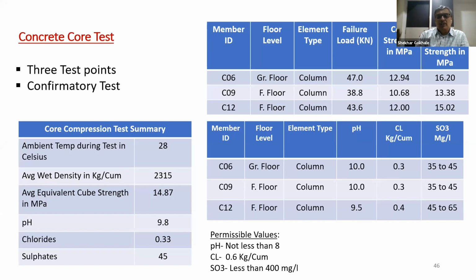The pH value observed was around 9.8 of the crushed core. After crushing, we took the pH value of that crushed sample, and the average pH value of 3 samples is 9.8, chlorides is 0.33, and sulfates is 45. So as far as pH value is concerned, it has reduced from 11 to 9.8, indicating carbonation of concrete. Chloride contents and sulfate contents are within the limits. Chloride should be below 0.6 and sulfate should be less than 400 milligram per liter. So for chlorides and sulfates, there is no issue. The pH reduction indicates carbonation of concrete, and the cube strength, which we can say is a confirmatory test, is near about M15.